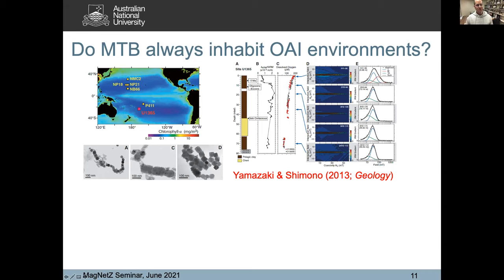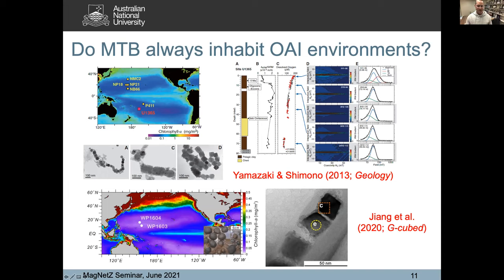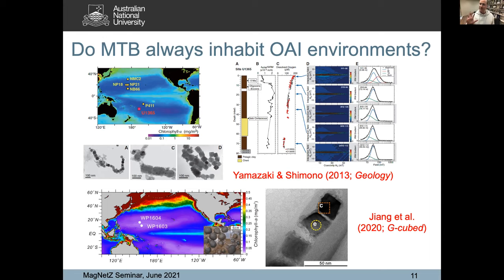And you get these beautiful equidimensional octahedral magnetofossils with all the normal magnetic indicators of their presence. Shadong Zhang worked in our group and in Ching Song's group at Sustech, and looking at ferromanganese nodules on the sea floor in the Pacific, the magnetic signal in these nodules is carried by biogenic magnetite — several groups have discovered this almost simultaneously. I would argue that we're not part of an OAI here — it's oxic, maybe nitrogenous in places, but we're in really the upper part of any redox zonation. These organisms love redox zonations, but this is not an OAI — it's miles above it.